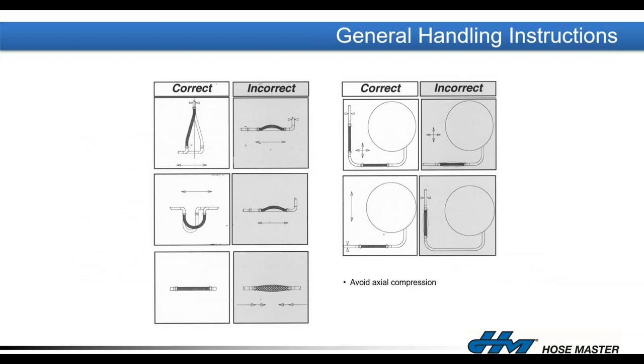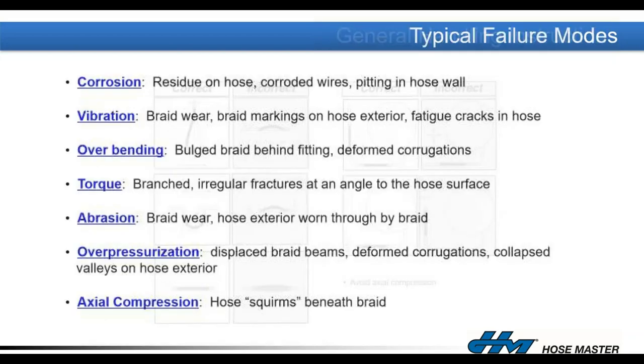In the left-hand set of diagrams, either the hose is being compressed, causing it to bend out of its own way, or, what's very common with pump connectors, I've got a picture coming up, the bottom gray diagram is where the hose is being compressed in line with itself, causing the braid to bag away from that hose. That hose now only has the working pressure of its unbraided hose, which is much, much lower, and that hose will squirm and deform and fatigue and fail if that braid is allowed to slack away from the hose.